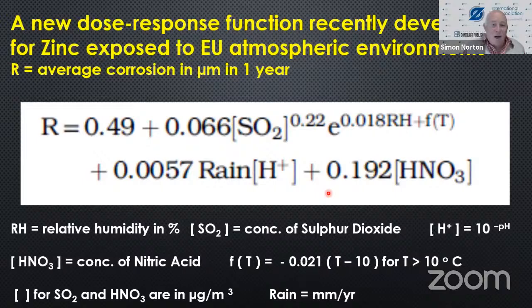Thank you. A new model has recently been developed for zinc exposed in the European atmospheric environment, which is quite interesting. This equation, which I won't deal with in too much detail, but merely to expose you to the thinking that's going on, has a 0.49 factor for the background corrosion. This factor over here with SO2, the relative humidity and the temperature, or the function of temperature, is what's called the dry deposition, because it's been found that as temperature increases, a certain point is reached where sulfur dioxide corrosion then stops, because it's very temperature dependent.